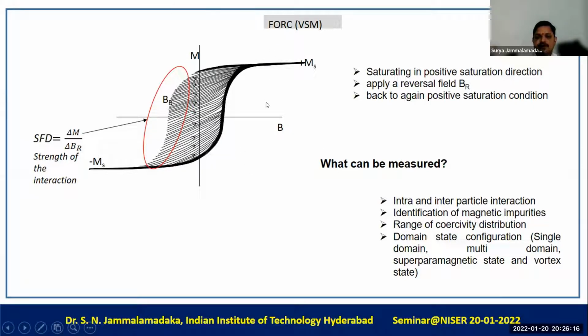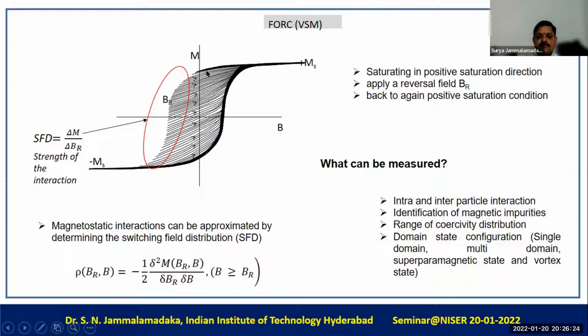So on all the films, we tried to do FORC curves. In a short while, I'm going to show you those results. Another most important parameter that one can obtain using the FORC curves is the switching field distribution. The magnetostatic interactions can also be approximated by determining the switching field distribution. The distribution function is basically minus half del square M by del BR, so the double derivative of the magnetization with respect to the reversal magnetic field.